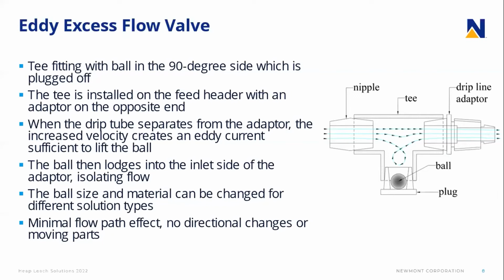With this one, it can be modified quite a bit. We were using Y-type fittings or T-type fittings, but the ball size and material can be changed. We initially started with glass marbles, found that they were not very uniform in size, so we switched to 3/16 steel balls, and sometimes we would put 2 balls in them or extend it up and down, so you can get a different height in the bottom, which causes it to go off at a lower pressure or a higher pressure, whichever you prefer.